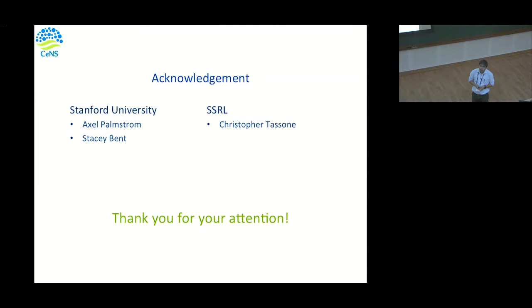How thick are these layers? So these layers are around 30 nanometers thick. Can you make them extremely thin, like a couple of layers? So one monolayer can be done. The only problem when you go to a very thin layer is that the uniformity of the film is going to be a little bit problematic. But it is possible to do it.